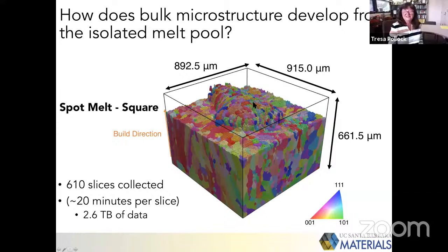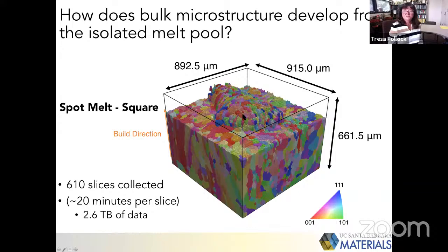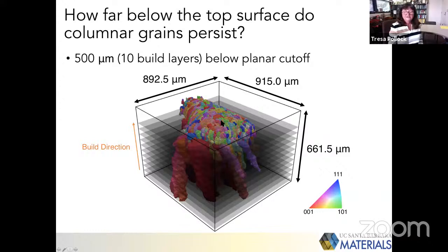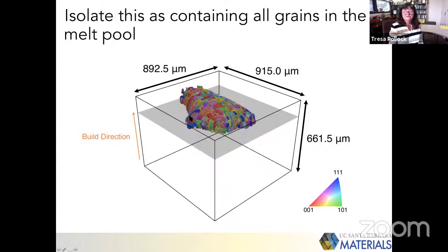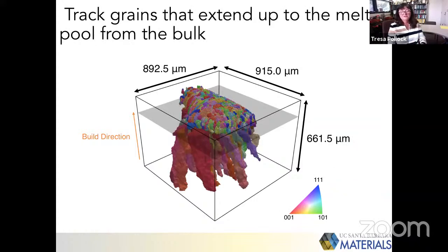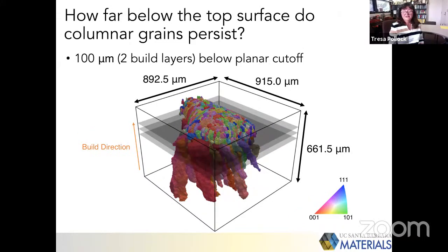Okay, so here now we have this spot, and you can see that the conditions in the melt pool were completely different. And so again, we want to understand how this structure developed, and so we can track the grains back through the layers. So here is the top of the melt, and here are the grains that extend into the previous layer, into the previous layer, and so forth.